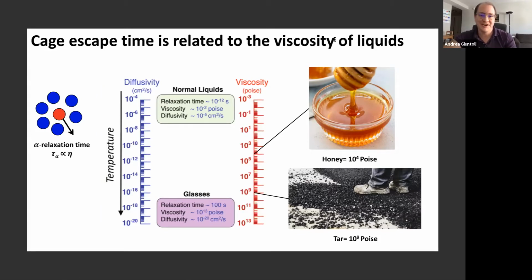To give you an idea, in this range, the viscosity will increase from 10 to the minus 2 poise for water. Then you have, for example, honey, which has a viscosity of 10 to the 4 poise. So that's 6 orders of magnitude larger. Then you go to tar, for example, which is a highly viscous liquid with a viscosity of 10 to the 9. So that's another 5 orders of magnitude. If you go 4 orders of magnitude beyond that, at 10 to the 13 poise, that's where we define glasses. So remember that a lot of the materials you use in your real life, polymeric materials, plastics, so many of them are formally in the liquid phase, but they just flow so slowly that you can wait your whole lifetime and you'll never see them move.